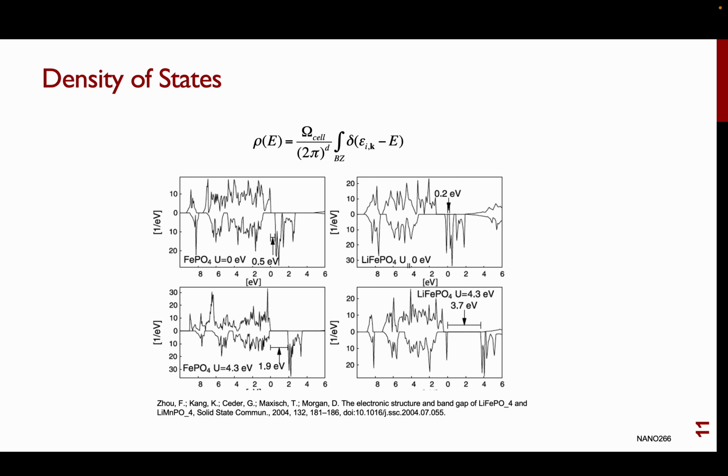Okay, and this is contrary to whatever we know about these two materials, right? Experimentally, they have very low electronic conductivity, so their band gaps definitely should be much wider. Now, this will also show that if you actually apply a Hubbard U value to your calculations to properly localize the electrons in the d orbitals of your iron, the band gaps are actually much wider, and this is more in line with what is experimentally measured. Okay.